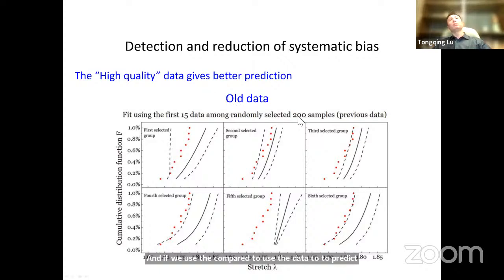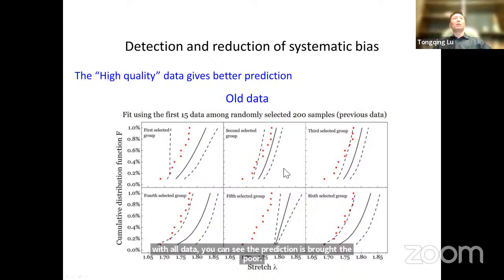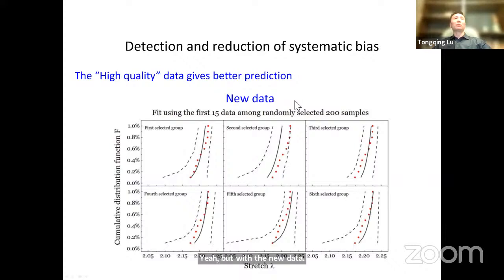You remember previously, if we use 1,000 samples to predict a rare event, the prediction is okay. But if we use 200 samples with the old data, you can see the prediction is rather poor. But with the new data, with the new experimental setup, we can see even if we use only 200 samples, the prediction is much better and it's very stable. We can repeat this analysis 6 times, randomly selecting, and each time we get a very good prediction. So of course, the new data gives much better prediction than the old data.